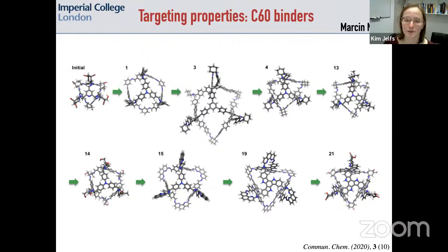And in this case, this was a particular case study where we were looking at C60 binders. So we were trying to find a porous molecule that could do a good job of absorbing C60. And what I'm showing here is the top candidate at any given generation. So there'll be, say, 64 candidates in a generation, but I'm showing you the best one. And then what's numbered is the generation number. So at the initial guess, that's largely random, it formed a cage that really isn't big enough for C60. By the next generation, generation 1, the cage has got a bit larger. And then it slightly overdid that.